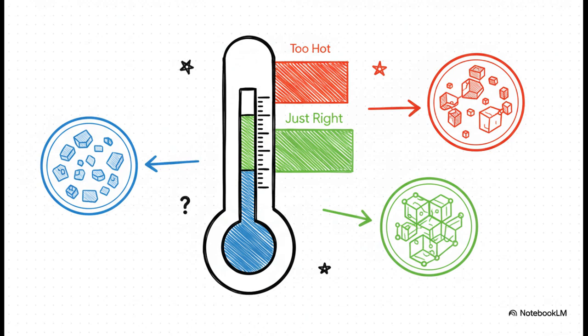If you're a little too cool, not everything dissolves, and you lose a ton of potential strength. If you're even a little too hot, the metal can actually start to melt on a microscopic level, creating weak spots that ruin it. This is not like baking cookies, where a few extra degrees doesn't matter. Here, precision is absolutely everything.